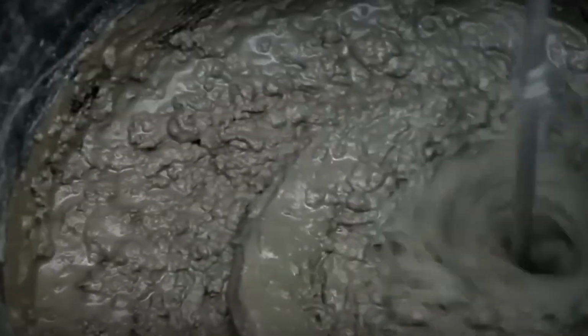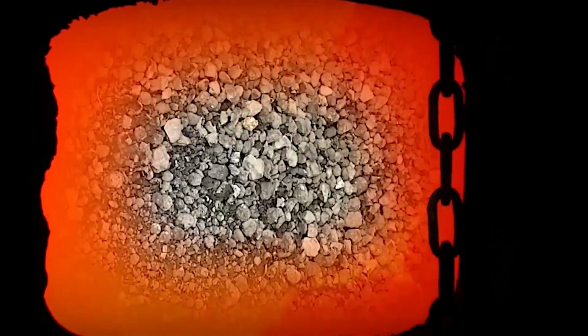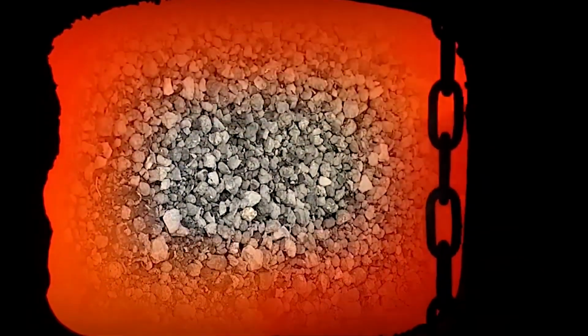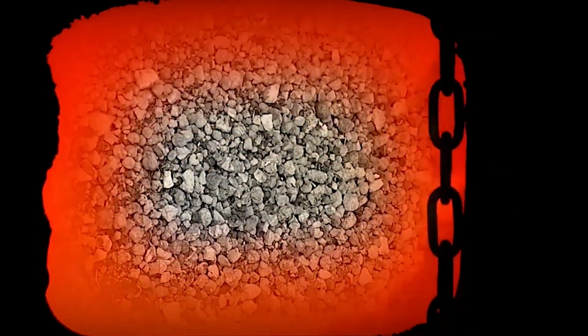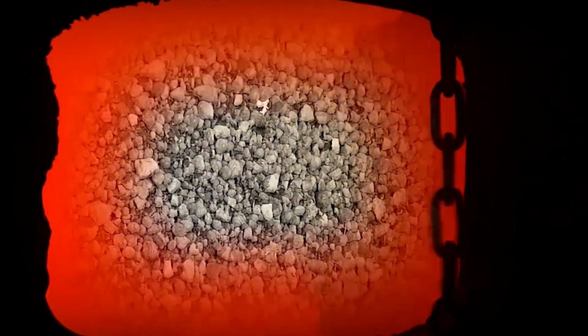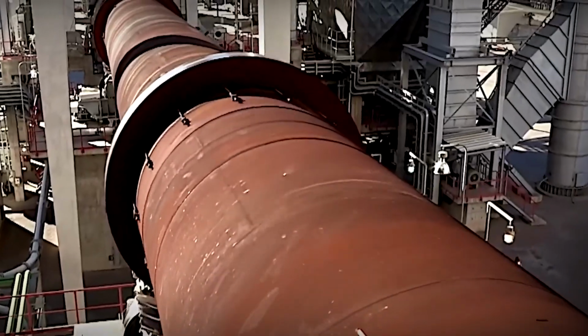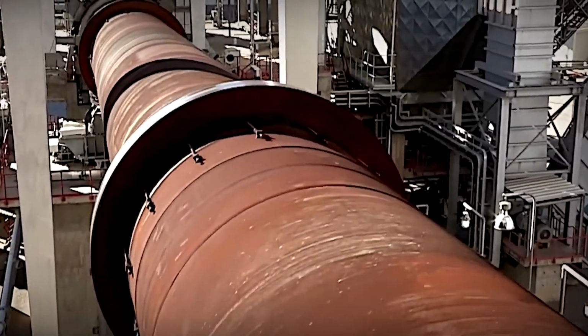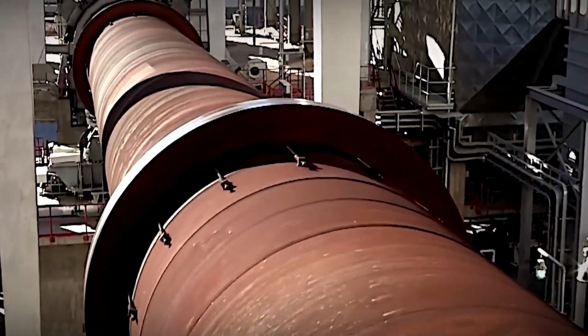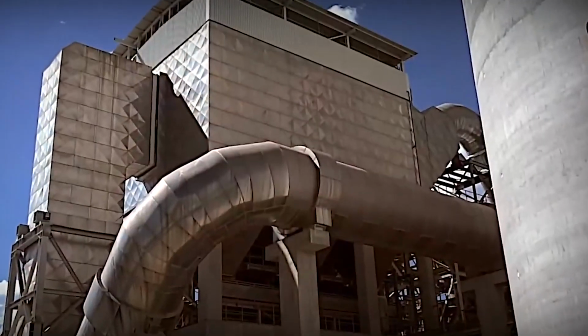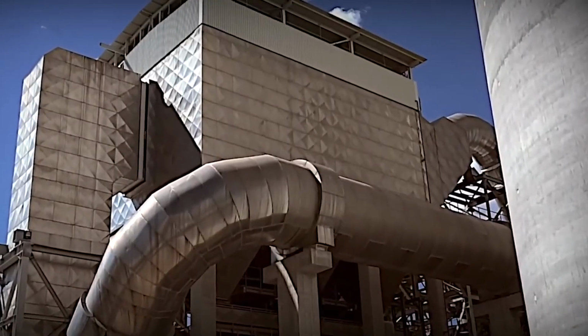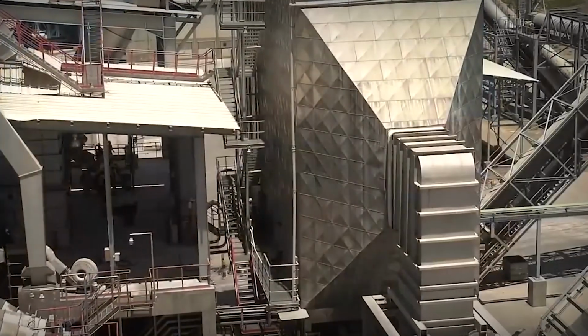After preheating, the material enters the most important part of the process, the rotary kiln. This massive cylindrical furnace is slightly tilted and rotates slowly. It can be over 100 meters long and operates at temperatures reaching around 1450 degrees C. As the raw meal travels through the kiln, it undergoes a series of complex chemical reactions. One of the key reactions is calcination, where calcium carbonate in limestone breaks down into calcium oxide and carbon dioxide.